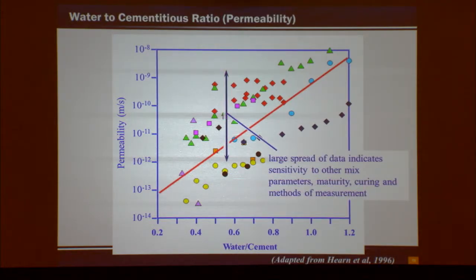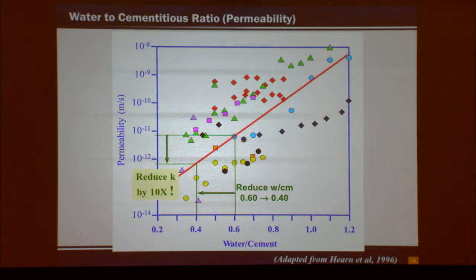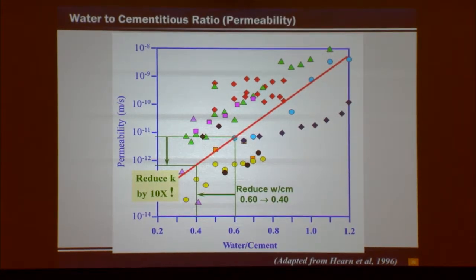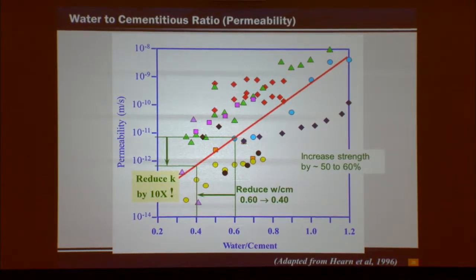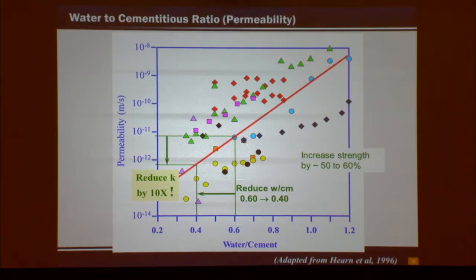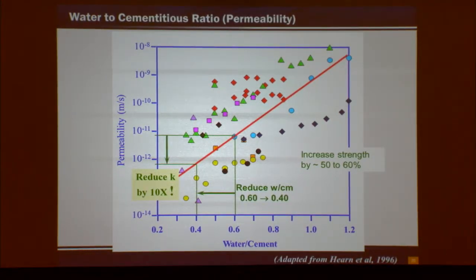Again, there is some large spread, meaning there are other factors that control permeability. However, water-cement ratio is a fairly large lever arm in terms of permeability. We could get some substantial reductions in permeability if we reduce the water-cement ratio slightly. What's our specification for max water-cement ratio for most concrete? We're at about a 0.45 limit, right? So we're somewhere around here, right? So we lowered that limit over the years to try to get less permeable concrete out there in our structures. We also get a strength increase with the lower water-cement ratio as well. That necessarily isn't always a good thing, but it does come along for the ride.